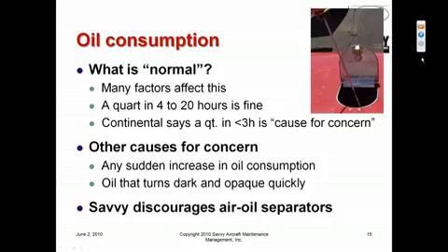And we don't know whether what changed is serious or not before we do some troubleshooting. So any sudden increase in oil consumption is certainly worth doing some detective work to try to find out why it's happening. And it may turn out that it's happening for a completely innocuous reason. All kinds of things can cause a sudden increase in oil consumption. A gasket on an oil filler cap that isn't sealing real well, so it's allowing pressurized air into the crankcase when we're flying the airplane, can increase crankcase pressure and shove a bunch of oil out the breather. A bad front crankshaft seal can do the same thing, and those are not serious problems, and we can certainly live with them until the next convenient maintenance interval when we can get it corrected.